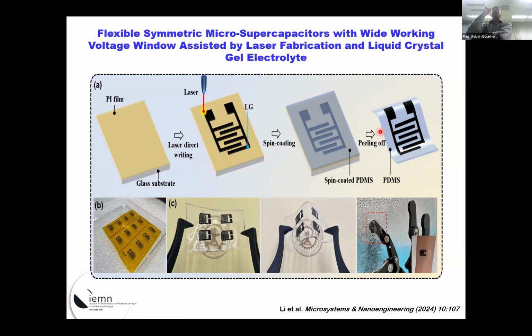So here we start with polyimide. Indeed, we use a CO2 laser the same way. You can write your electrodes here, the positive and the negative electrode, the same way, by just optimizing the conditions. Then what we did, we just spin coat PDMS on top of this. You peel off, and then your electrodes are transferred very nicely to your PDMS.